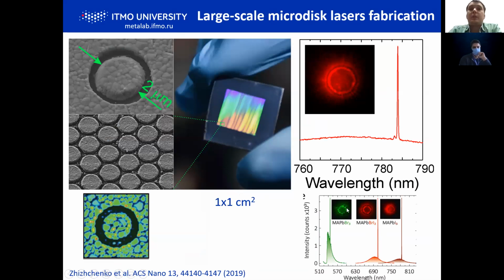And it works. So why does it work for lasing? Because after PL mapping of such a micro disk, we see that there is no damage and no quenching of photoluminescence after laser ablation, despite the fact that we strongly heat this area and remove the material. Perovskite doesn't lose its light-emitting properties. And it works for different compositions, for green perovskites, for red perovskites.